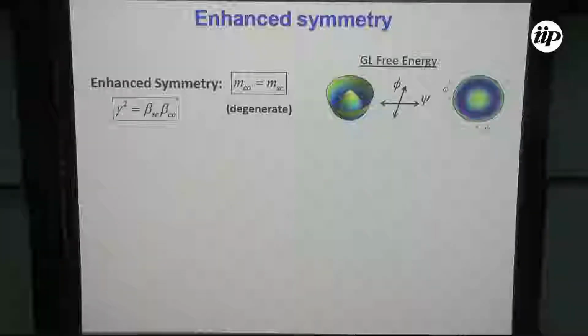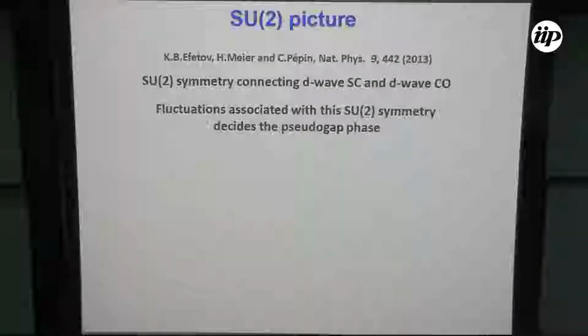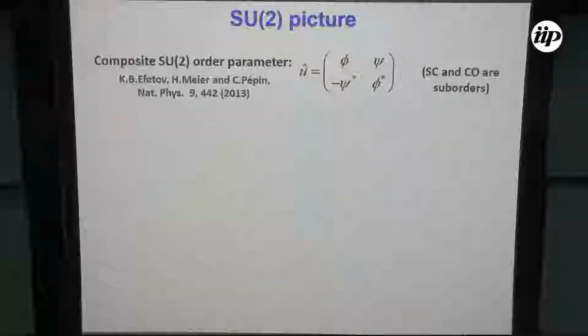So as a result, we have an enhanced symmetry from a lower symmetry group, which was just superconductivity and charge order. Similar enhanced symmetry was studied by Efetov and Pépin 5 years back. So what they found is that there is an SU(2) symmetry between d-wave charge order and d-wave superconducting order in underdoped cuprates. And the fluctuation between these two orders gives rise to the pseudogap phase at higher temperature. Within this picture, you can actually write a composite order parameter.